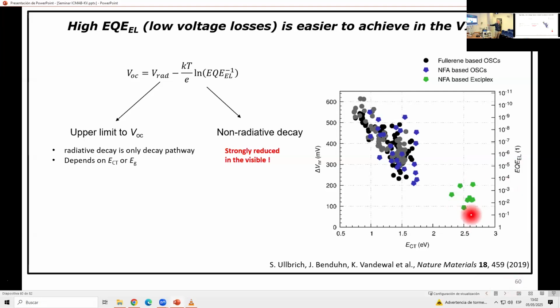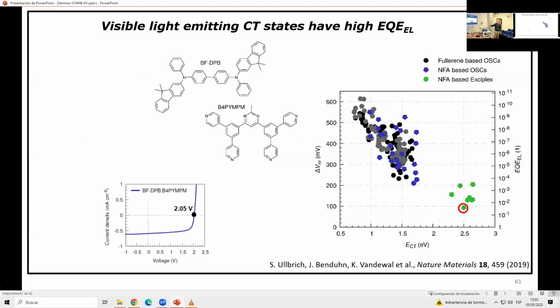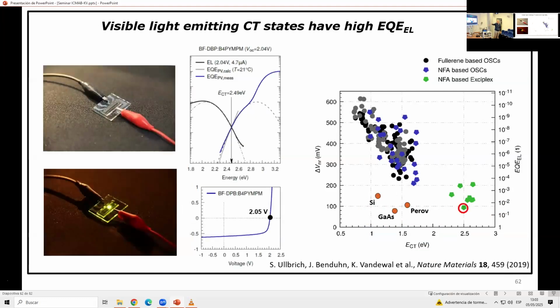They have really low voltage losses and they're actually good LEDs. So it is possible with organics to have very low voltage losses here in the visible, where also the organic solar cells work. But in the infrared, not yet. This is one of them. It looks like this because it's visible light emitting. So it's both LED and solar cell. Nice IV curve, I would say, just a low current. In terms of voltage losses, it does the same as the inorganics. It's equally good, but not at those gaps.